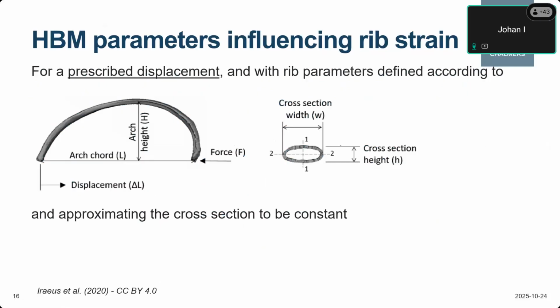If we start with something simplified, for a prescribed displacement, with the rib parameters defined according to below, we have the arc chord length and we have the arc height length. We have a rotating end here, and we have a prescribed displacement over here. We simplify the cross-section as an elliptic cross-section, so we have a width and a height of the cross-section. And we also approximate these cross-sections to be constant over the rib, which is not true in reality,